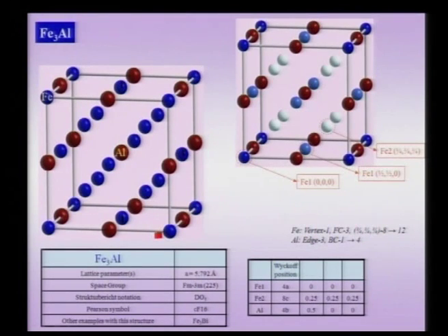And let me count the number of aluminum atoms. The aluminum atoms are the ones which are in brown, and you can see they are all located at the 12 edges. So, from 12 edges with 1/4 contribution to this unit cell from each edge, I have 3 aluminum atoms which come from the edges. There is one more aluminum atom located at the body center, which gives a contribution of 1, therefore a total of 4 aluminum atoms in this unit cell.